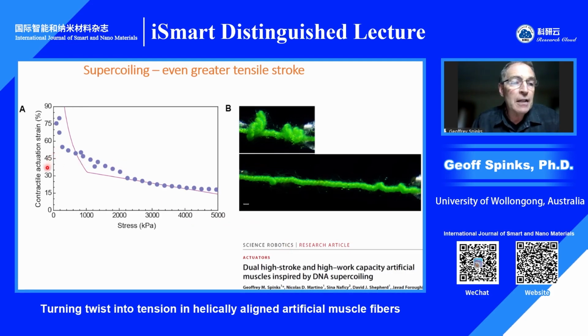So in the chart in section A here, where we're seeing the actuation strain, this is contractile, so it's represented as a positive number, but it actually is in contraction. And you can see from the data points that we're getting contractions up to 80% of the starting length. And at appreciable stresses as well. It does decrease, of course, as we increase the stress. But below 1 megapascal, the actuation strokes are above 50%.